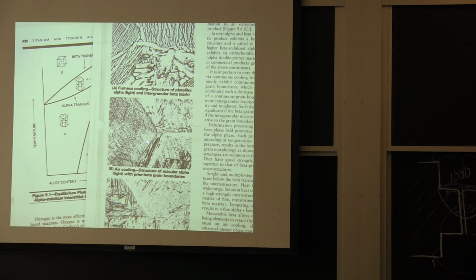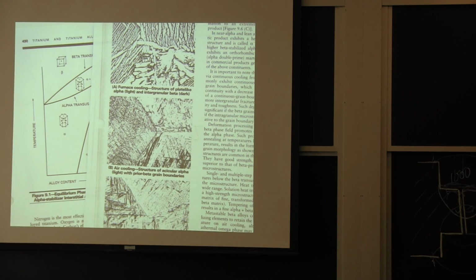But you actually get what we call basket weave morphology. And so you get grains crossing each other because you nucleate, and you get anisotropic growth because of the anisotropic crystal. But that actually gives you a very favorable, very fine grain, very mixed up crystal structure, which is one of the things that gives you good strength. It turns out the welds in titanium have better fatigue strength than the base metal because they have a finer